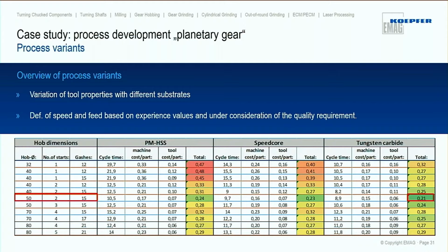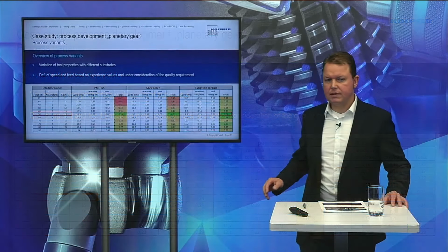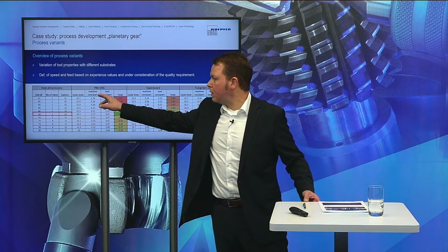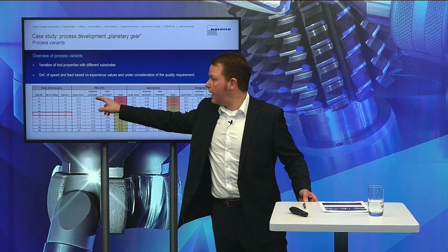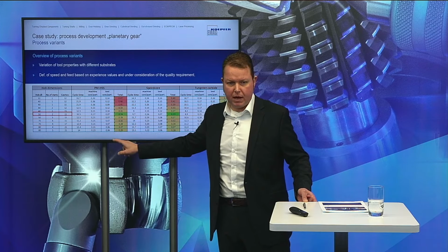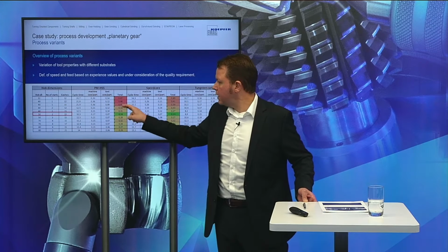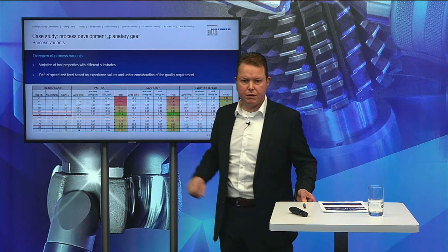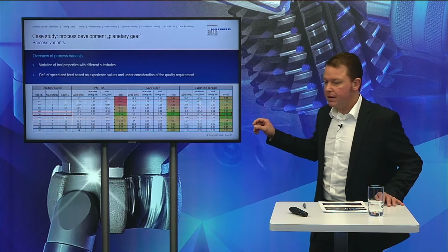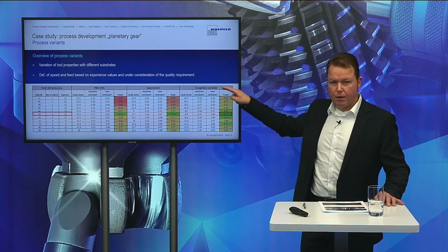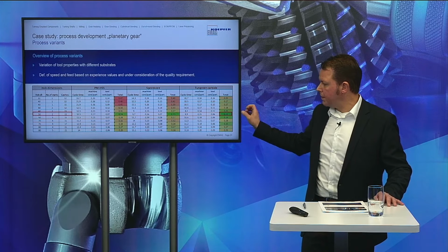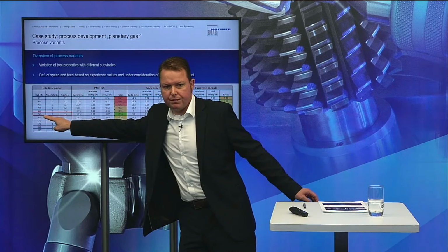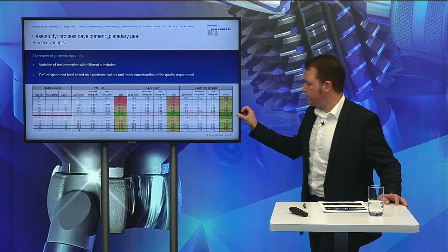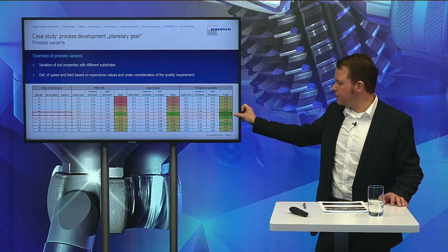We have done this for PM-HSS as a substrate with coating, speed core with coating, and tungsten carbide as well. We have the cycle time. Besides the cycle time, we have the machining cost per part, and we have also the tool cost per part. And if we add up these figures, we have the total cost for each individual machining process. And you will see one thing, there is a minimum here for the tungsten carbide tool with coating. With this geometry, diameter 50, 2 starts and 15 gashes, we have the highest efficiency in the gear hobbing process.